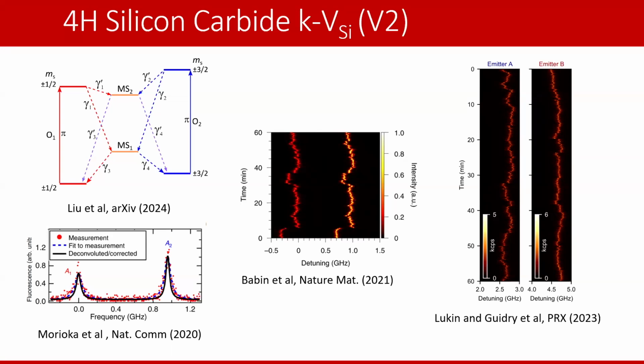So the level structure looks a little bit like this up here in the corner. There's a spin 1/2 and a spin 3/2 transition. These are optically accessible and spin preserving. There are two metastable states in the center with these intersystem crossings, and this is not great. If you're comparing the silicon vacancy to other defects, the main issue really is going to be the cyclicity of these optical transitions. That provides a big issue